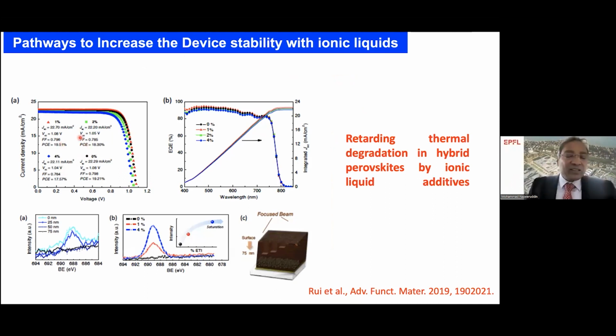The IV data, the photovoltaic performance, is almost the same with small differences. The best efficiencies are close to 20% with 1%. The reference sample is 19%, but in between we have this one data. That's not the important point which I want to highlight here. Actually, to understand what is happening with this ionic liquid, if you look at one grain, take one grain. Before we take one grain, let me give you the reference fluorine binding energy. You take any sample, fluorine binding energy, you get around 689. This is the peak coming from the fluorine binding energy.